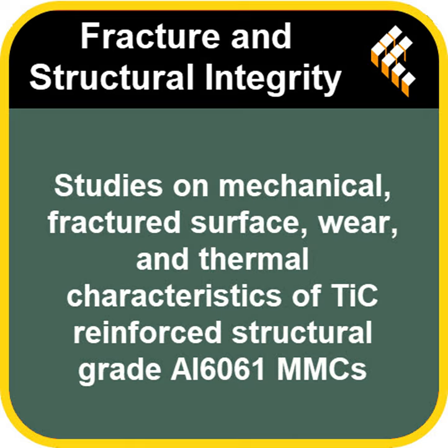The study reported a significant minimization of wear loss by about 40%. Wow, 40% less wear. That's a huge improvement in durability for many parts. Did you get a visual confirmation of this improvement? Could they see the difference? They certainly did. They used scanning electron microscopy, SEM, to meticulously examine the worn surfaces, and the images clearly showed that the 9% TiC-reinforced composite had much smoother, more even sliding wear tracks, and noticeably less loose debris compared to the unreinforced Al6061 sample.